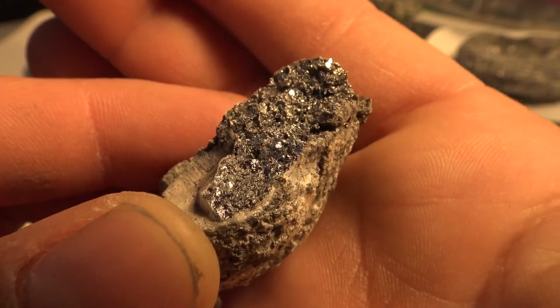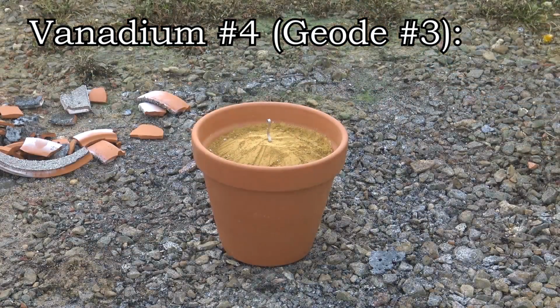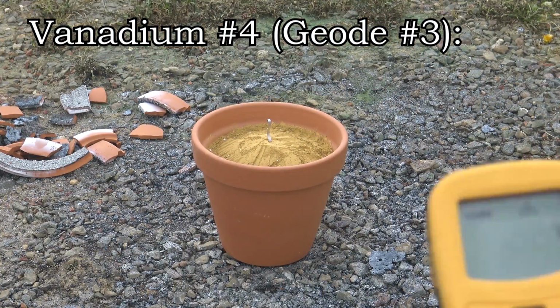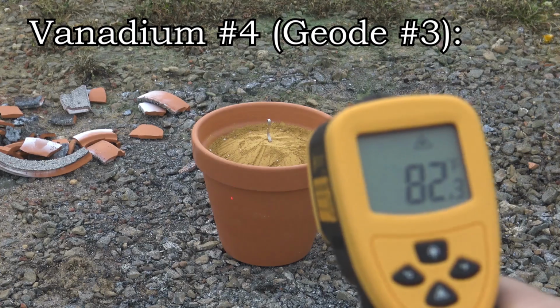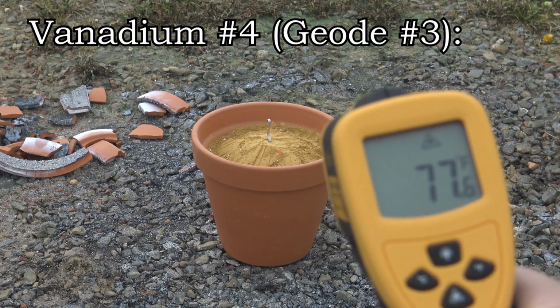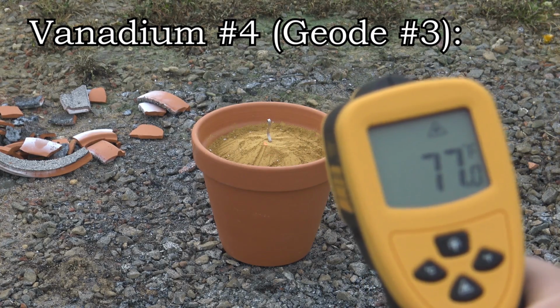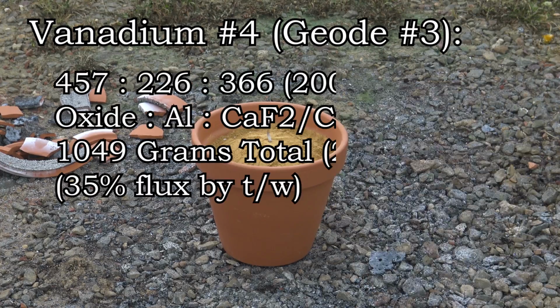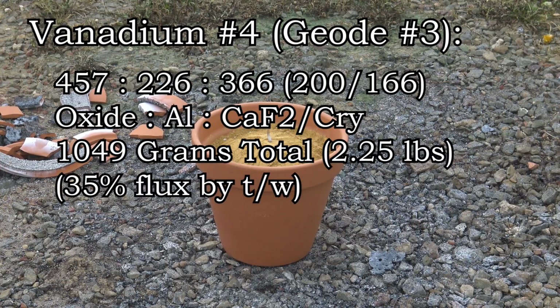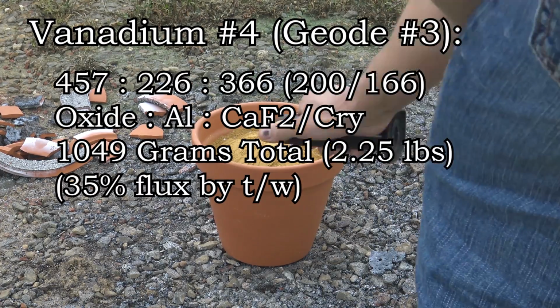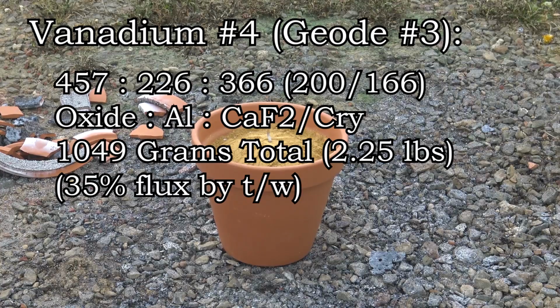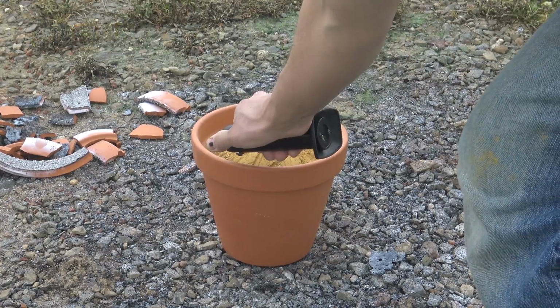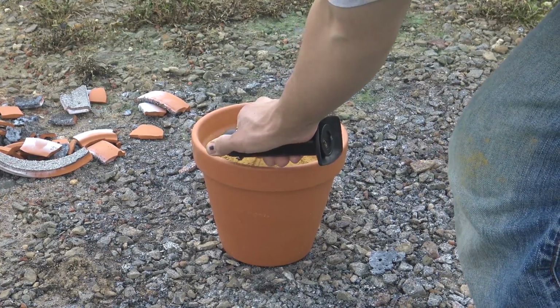Well, it looks like everything is taken care of except for one vanadium geode attempt. So let's finish this up. In the final attempt, we're going to reduce the flux from 40% to 35%, as that seems like the sweet spot to shoot for. Here's what the formula works out for, starting with 457 grams of oxide and totaling 1,049 grams or 2 1/4 pounds. I'll include better shots afterwards of all geode attempts so far.